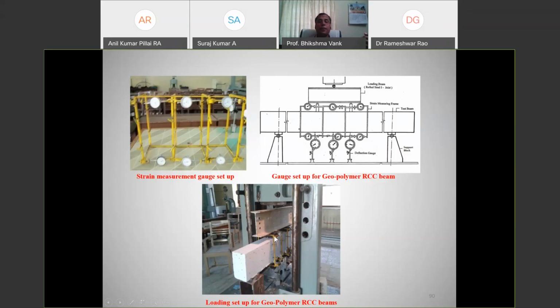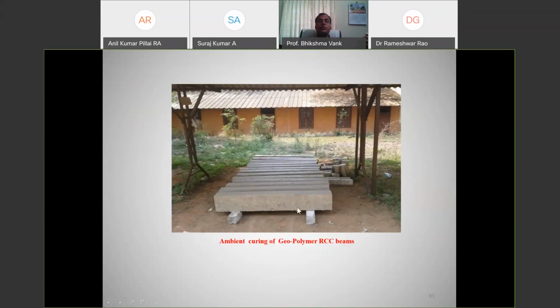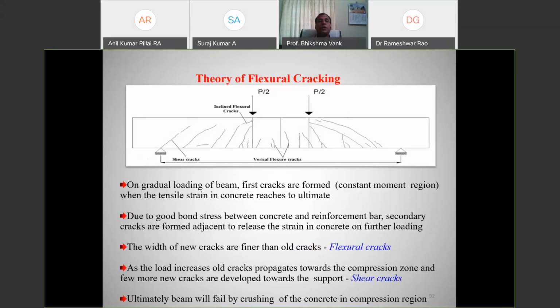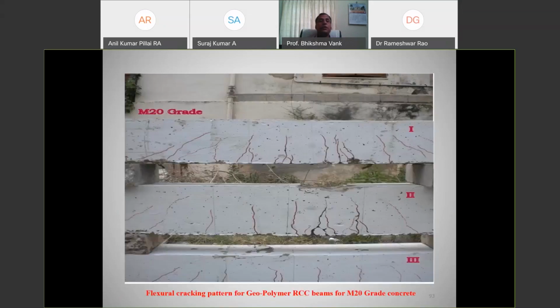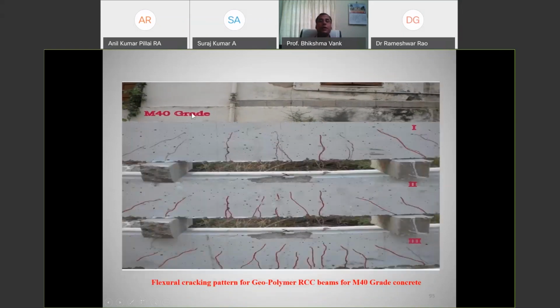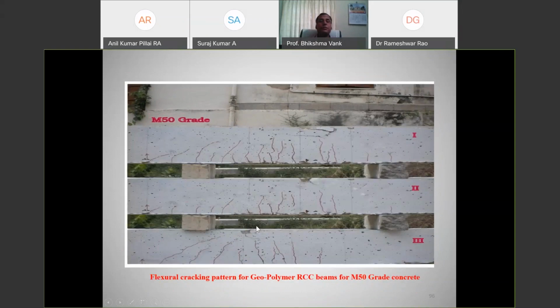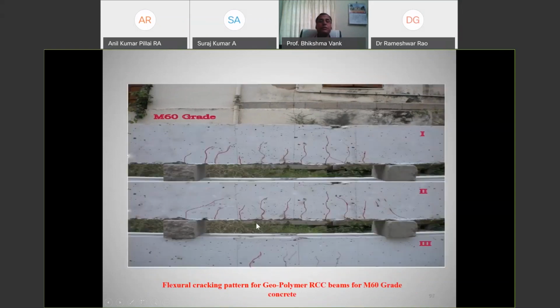2-point loading. This is the loading setup at Osmania University. These are all the beams, geopolymer concrete beams. They have not been cured; with ambient curing, they were left open to the air after casting the concrete. We kept them under the shed for 28 days, and after that we tested them. This is the loading pattern that we have taken. These are all the geopolymer concrete beams: M20 grade 3 specimens, M30 grade 3 specimens, M40 grade 3 specimens, M50 grade 3 specimens, M60 grade 3 specimens.